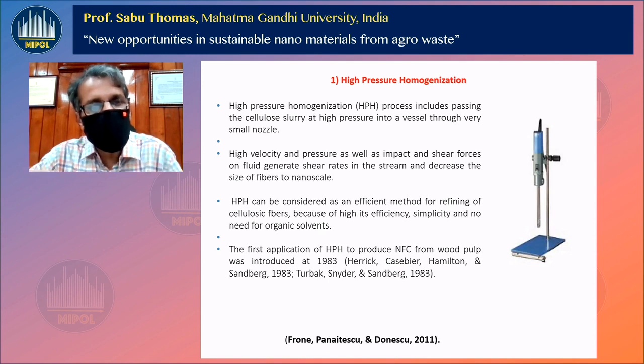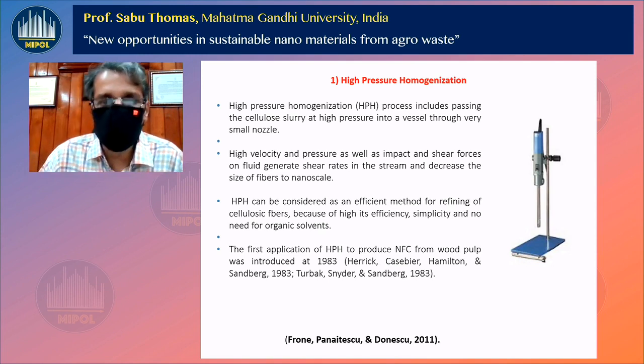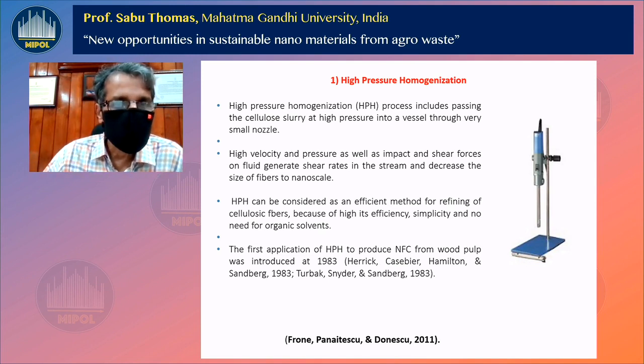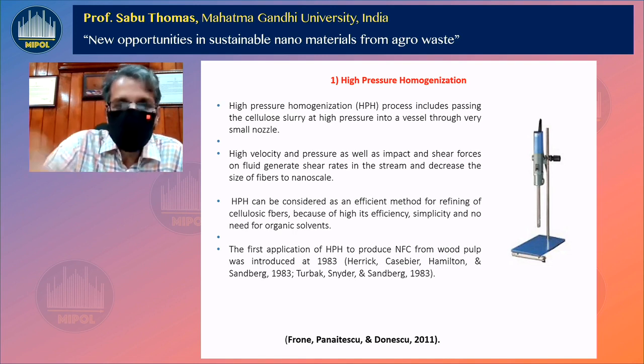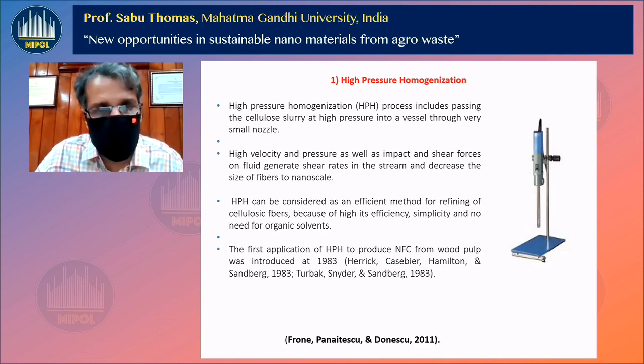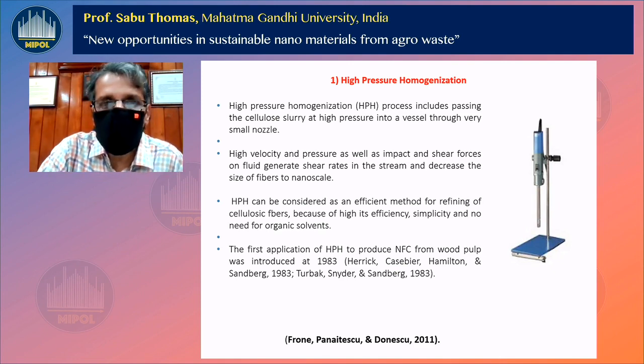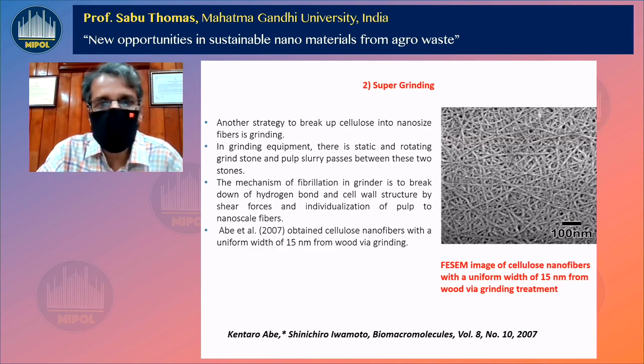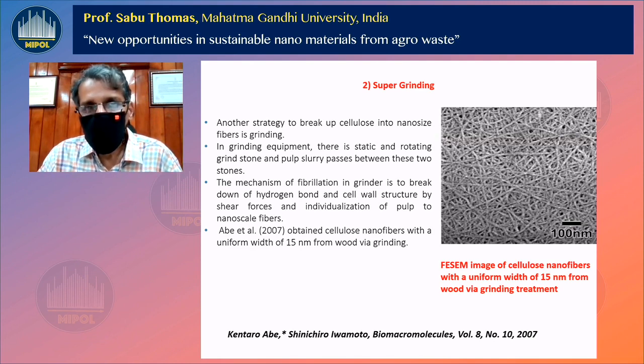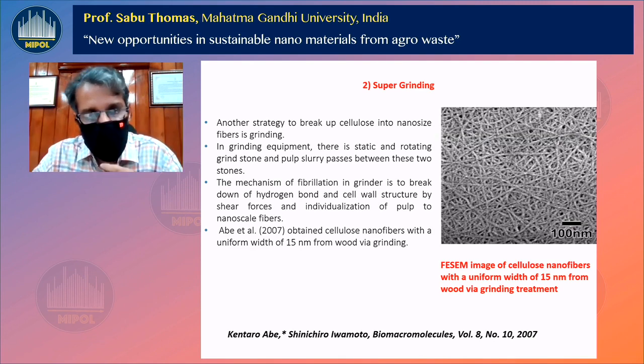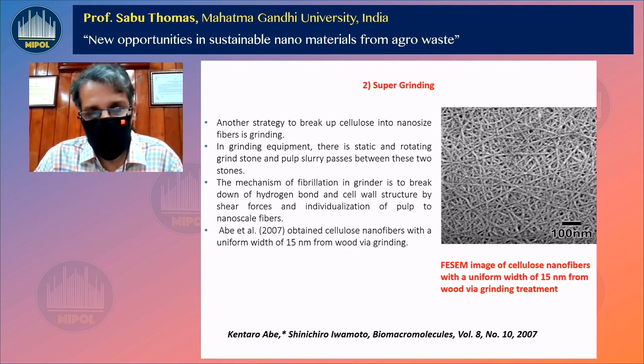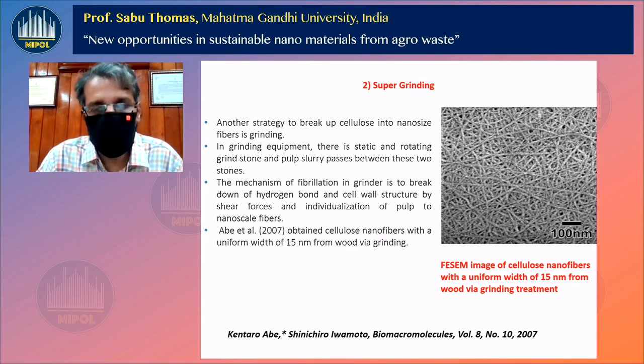It involves passing the cellulose slurry at high pressure into a vessel at very high velocity. That creates a lot of shear forces, and those shear forces decrease the size of the fibers. This is high pressure homogenization. You can also make it by super grinding. Professor Abe and group worked on this super grinding in Japan.